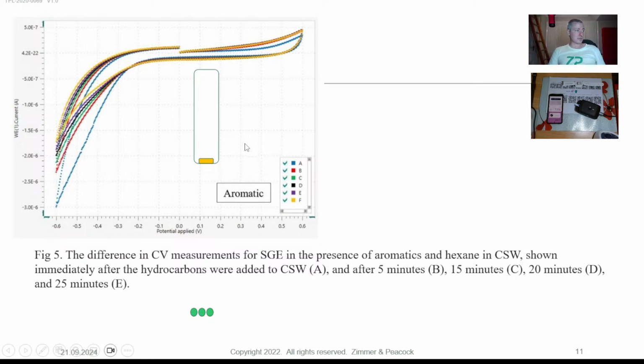Now, why is the signal decreasing with time? The reason is that this aromatic compound, I'm not entirely sure what the aromatic compound is, is adsorbing onto the surface. So it's essentially blocking the electrode to that oxygen reduction, because you have an opposite effect in a minute. Or no, actually you don't have an opposite effect. You don't have this effect.